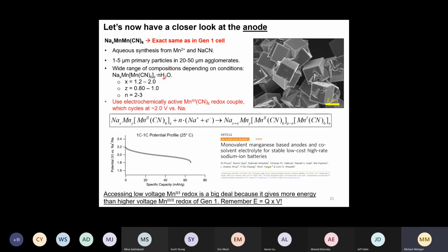So now there is one important difference to the first generation cell. In their second generation cell, they actually use the manganese 2+, 1+ redox of the manganese atom that is bound to the carbon, so the cyano group. And the cool thing is that this cycles at a voltage of about 2 volts versus sodium. You can see this in the voltage profile down here. So this is just this anode material versus a sodium metal. So that's why we get this potential here.